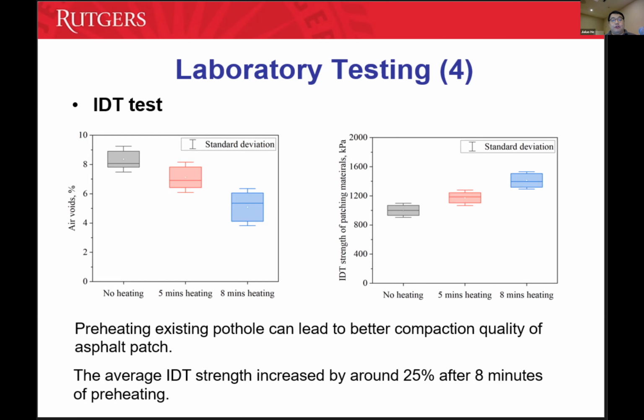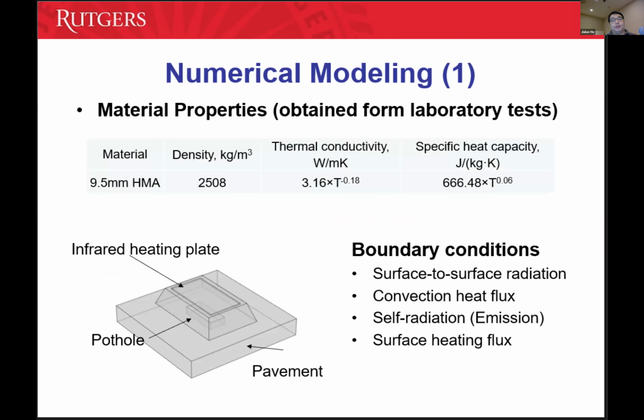But in the lab testing or field testing, we only have limited amounts of potholes. The shape is also fixed, and the infrared heater power is also fixed. This one we use a 4,500 watt. In the field, maybe you can adjust the power based on the pothole size. So how are these conditions affecting the heating? We started looking at how we can quickly develop a model for predicting the temperature increase, and this will help us decide the heating time requirements depending on all these conditions.